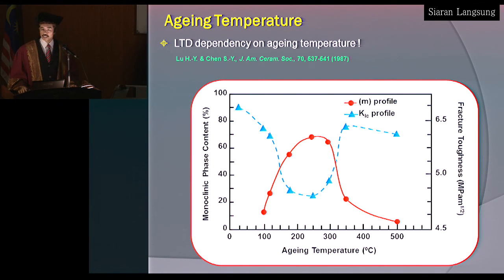Temperature has an effect as well. In the case of the femoral head, the earlier example, it is at body temperature. So temperature is low, but over a long period, it transforms. As temperature increases, so does the rate of phase transformation. What that graph shows, if you look at the red curve, is that maximum phase transformation takes place at about 200 to 300 degrees centigrade. During this period, there is a maximum drop in the mechanical properties as well. Aging at higher temperature has a lower effect, and aging at lower temperature has a lower effect as well, as shown by the red curve. At 100 degrees, the monoclinic phase content is low. So there's a temperature dependence in controlling LTD.